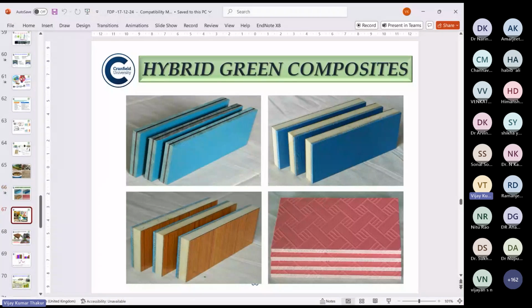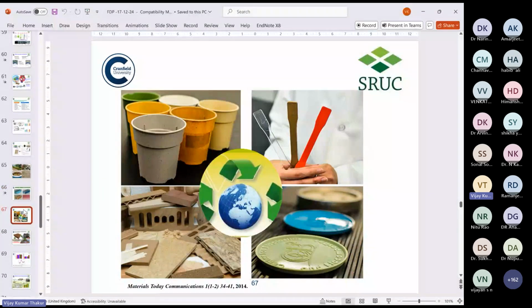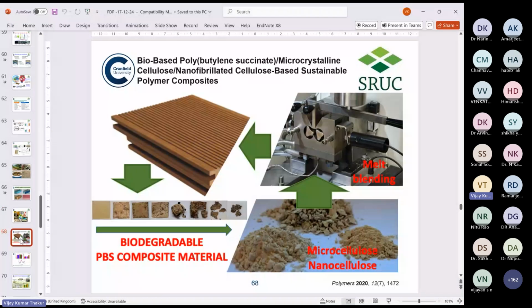Similarly, way back in the US, we developed a biodegradable container primarily made up of soya flour and biodegradable adhesive. The beauty of these materials was they can be easily biodegraded. So at the end of their life, they act as biodegradable. And we also made use of different thermoplastic materials. We have been looking into their synthesis as well as comparing them with their biodegradable component polymer. Here is one example of polybutylene succinate reinforced with microcrystalline cellulose and nanofibrillated cellulose.